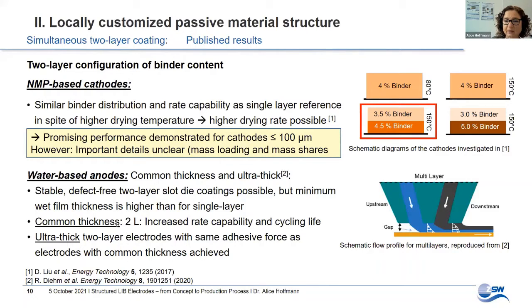But for common thickness in the two-layer configuration, an increased rate capability and cycle life was found. And in the ultra-thick configuration, also two-layer electrodes showed the same adhesive force as electrodes with common thickness. So in principle, the results showed also good properties of the two-layer electrodes.